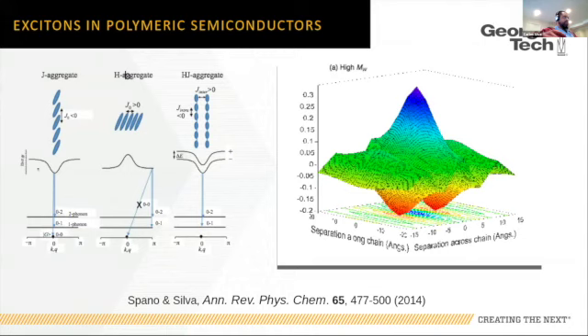Okay, and so we would lead to an exciton dispersion that has a minimum at the k equals 0 point. We can excite the exciton. Now, instead of having a collection of transition dipole moments, we have an in-phase addition of the transition dipole moments. This is called a J aggregate, right? We see a line narrowing of the emission, and it usually corresponds to a redshift with everything else being equal.